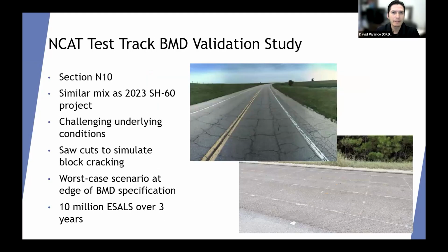In terms of the current test track study, we have section N10, and the idea there was to simulate the conditions of State Highway 60, which was one of the projects of 2023 we did in the state. It has very challenging underlying conditions. You can see the block cracking, a perfect example of the block cracking that we had on State Highway 60. What we did in the test track was to saw cut the section to simulate that same block cracking, and then basically recreate a worst-case scenario and use a mix that was at the edge of our BMD specification. Basically 25% RAP and a softer binder. That was pretty much the most challenging mix we allow in terms of our BMD special provision.